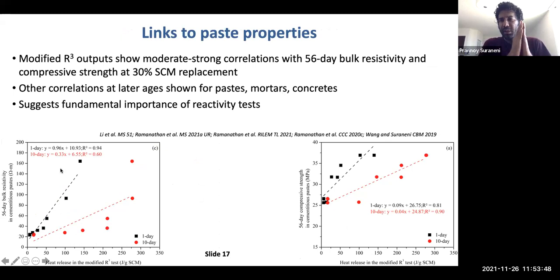Now, I've talked about reactivity quite a lot, but there is always the question, okay, you measure reactivity, but does it actually link at all to concrete properties? So I can tell you that it absolutely does link to cement-based properties. However, you want to be extremely careful when making such links. So we've shown, for example, that the bulk resistivity and the compressive strength at later ages, 56 or 91 days, show moderate to strong correlations with either the heat release or the calcium hydroxide consumption.